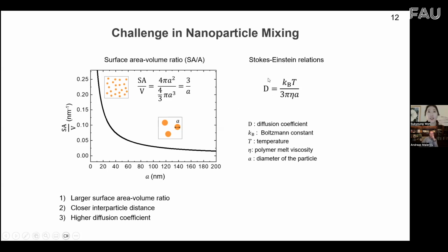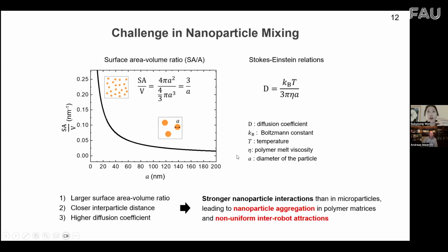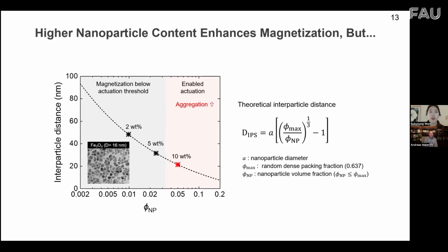Additionally, these nanoparticles have a high diffusion coefficient, meaning that they move easily within the composites. As a result, they exhibit a stronger interparticle interaction, leading to particle aggregation, and it could have a negative impact on the robot performance. Additionally, we require high nanoparticle concentration to obtain enough magnetization and actuation. However, as we can see in this graph, this decreases the interparticle distance and promotes nanoparticle aggregation.